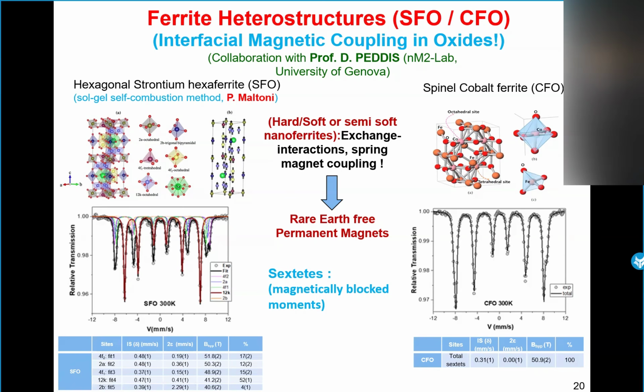We observe some overlapping, but the site 12K and the site 2B are well resolved at this temperature. Despite the overlapping, it's not a problem to reproduce the spectrum correctly using the 5 subspectra corresponding to the 5 sites of strontium hexaferrite, and the obtained percentage of each site corresponds to the theoretical value. That is because we have a correlation between the hyperfine field, quadrupolar shift, and isomer shift for each site.